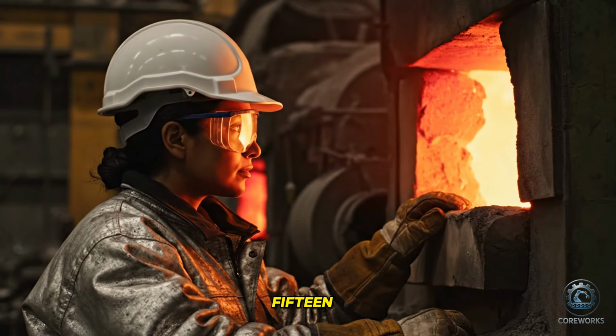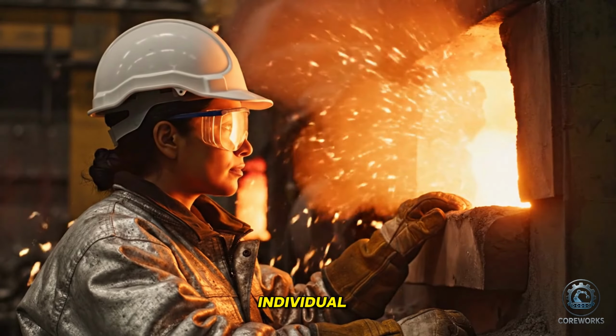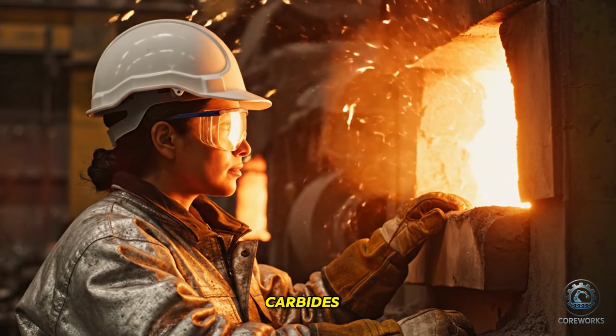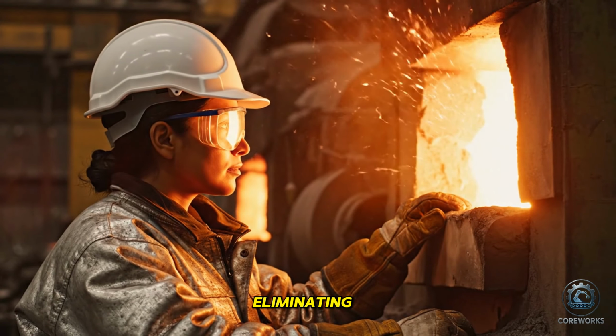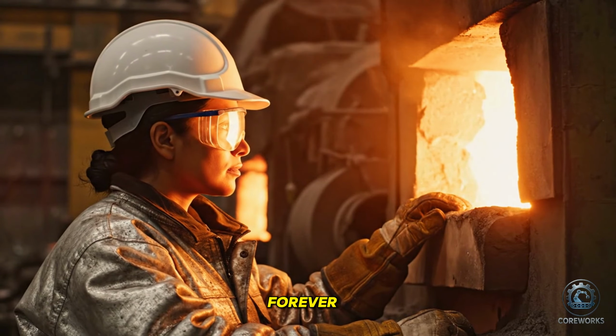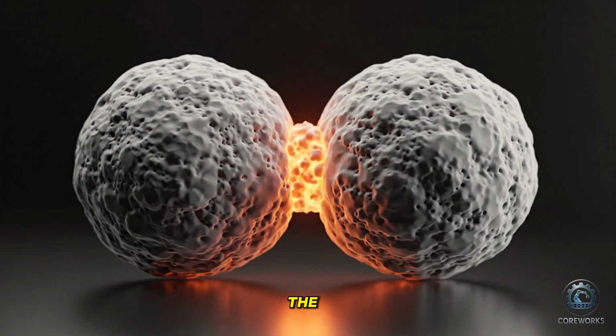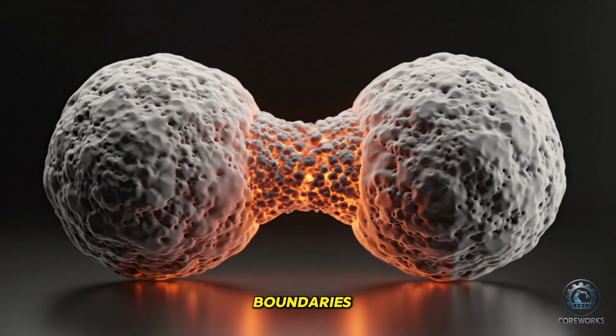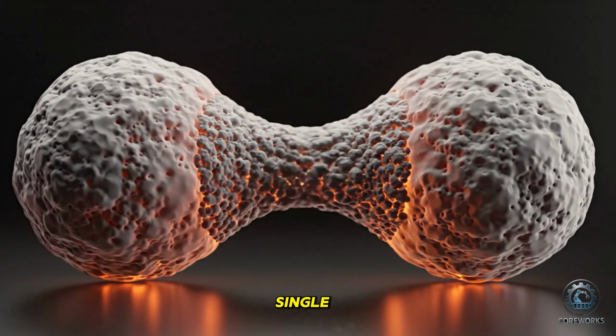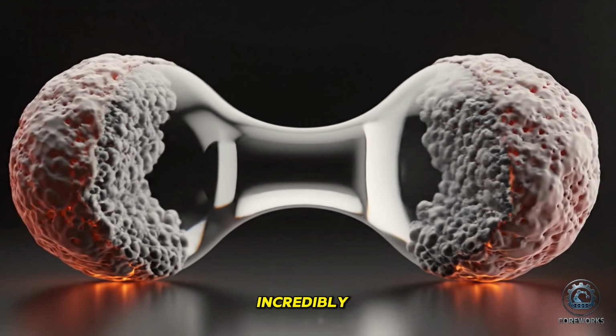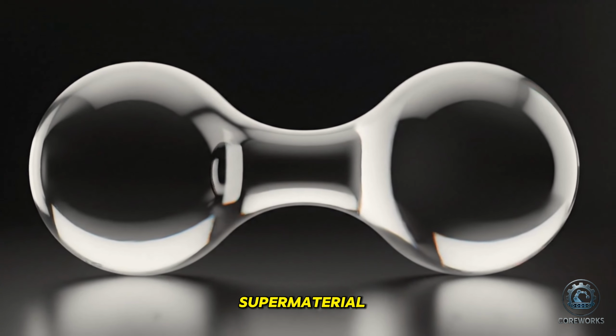As we reach 1500 degrees, the individual grains of alumina and silicon carbide start to fuse together, eliminating the spaces between them forever. This is sintering. The atoms migrate across grain boundaries, merging the powder into a single, dense, and incredibly hard solid block of supermaterial.